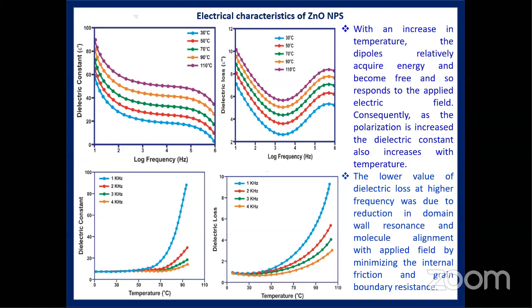And we also performed the electrical property study. You can see here the dielectric constant and dielectric loss at different temperatures with respect to frequency. Dielectric constant decreases with increasing frequency, and dielectric constant increases with increasing temperature. This graph shows the dielectric constant with respect to temperature at different frequencies. When the temperature increases, the dipoles acquire energy and become free, and so respond to the applied electric field. Therefore, the polarization increases, and the dielectric constant also increases with increasing temperature. And similarly, the dielectric loss with respect to temperature at different frequencies, 1 kilohertz, 2 kilohertz, 3 kilohertz, and 4 kilohertz.